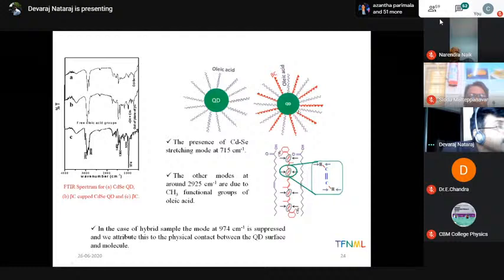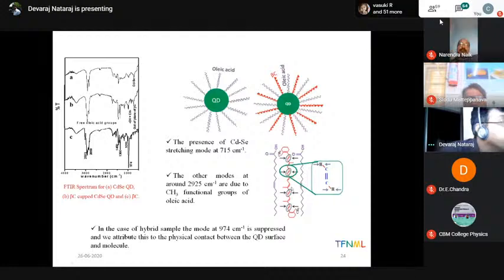And therefore, by observing this, we are able to confirm this molecule is having some kind of interaction, some kind of upright conformation. It means one end of the molecule is in contact with the quantum dot surface, not the entire molecule. And we have seen that the emission is increasing and the tip of the emission band is shifting towards the blue side, and these are all indications that beta-carotene is having some kind of type 1